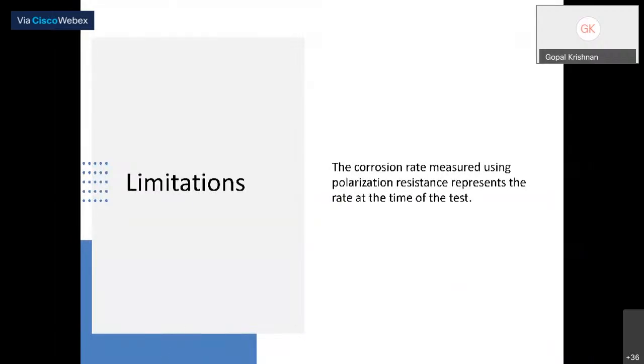So the corrosion rate measured using polarization resistance represents the rate at the time of the test only. These are limitations in this particular test, because corrosion rate is going to happen continuously, it may change.